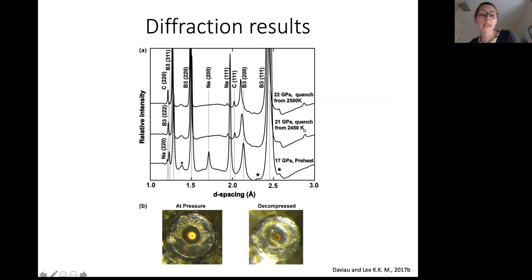What we also observe is that as you heat it, there are very dramatic optical changes in the silicon carbide sample. Down here, looking at this at-pressure image of the sample, this is looking down, map view, at our sample chamber. The outer region is the unheated silicon carbide on the edges of the sample chamber and outside of the laser spot. This inner region that's transparent, with the backlit light coming through, is where the heating spot was focused. And right in the center is where it got the hottest. You can see it turned more opaque and dark in the center. And these features stick around even after the sample is decompressed. So you still have that more transparent region and then that darker, more opaque region in the center in that decompression image on the right.